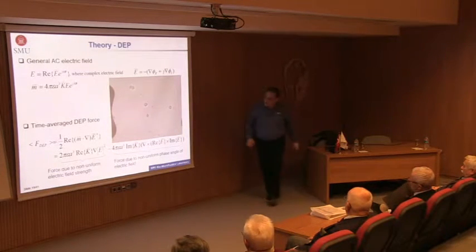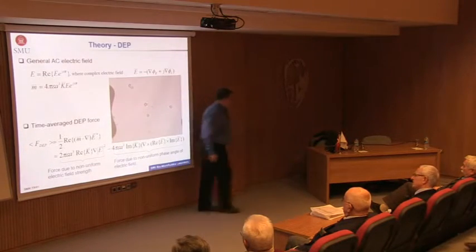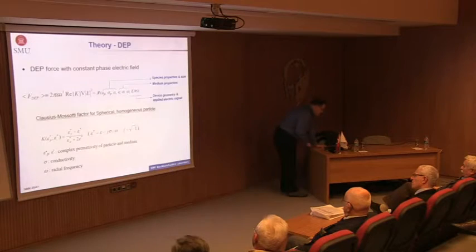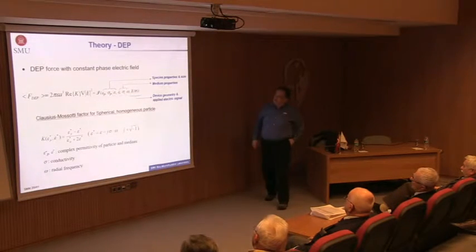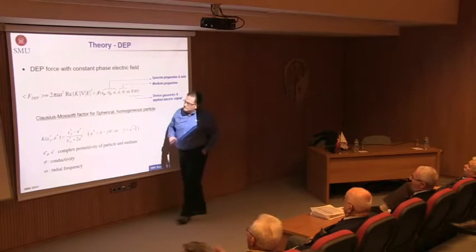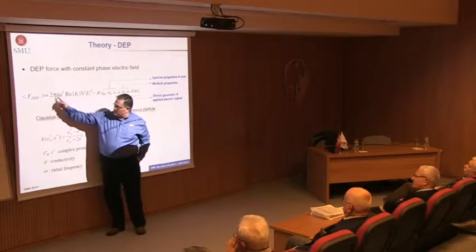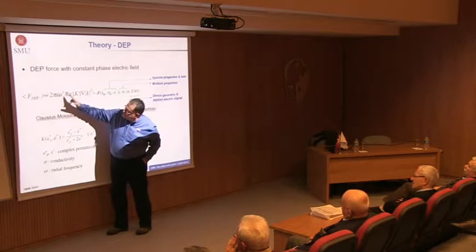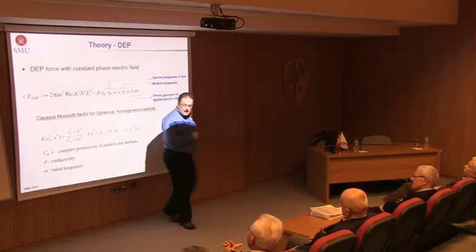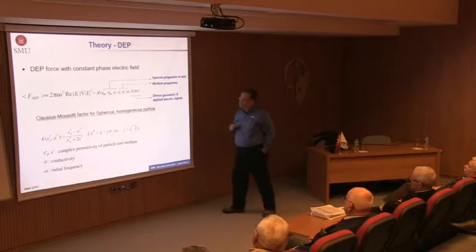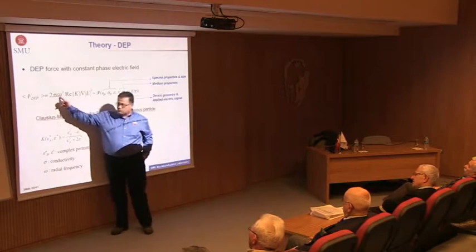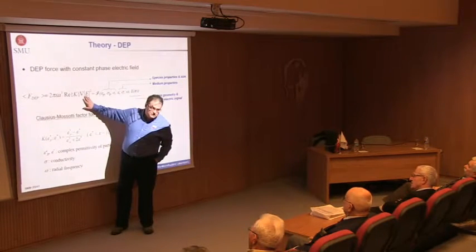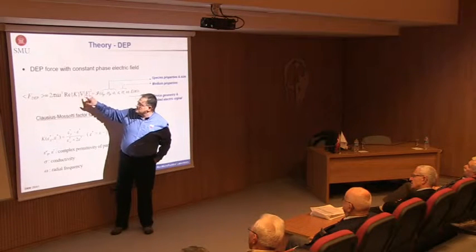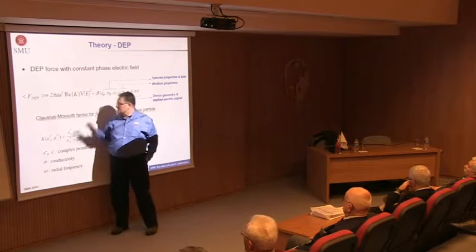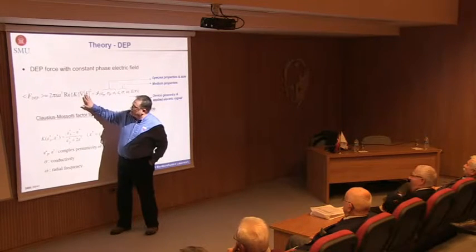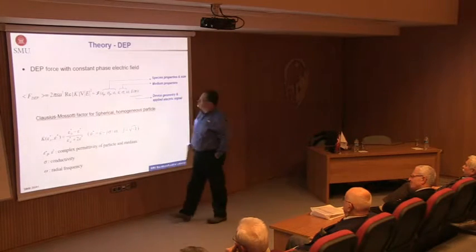Instead, I focused on this easier component and will tell you the things that we have done. When you look into the DEP force with constant phase electric field, it is first of all proportional to the cube of the radius of the particle, which makes it extremely effective for microscale, and which is good for biological cells. But viruses being in the nanoscale, the DEP force is going to be very small unless you have a very large electric field, and that may require sub-micron scale electrodes to deal with viruses, which we are not doing. But micron scale electrodes with biological cells work extremely well.